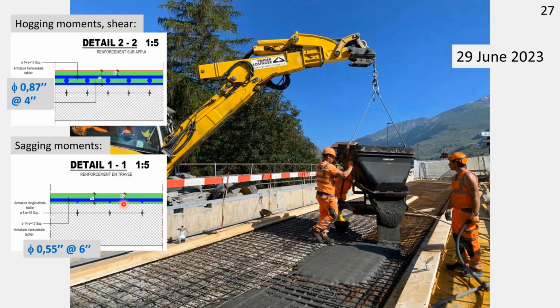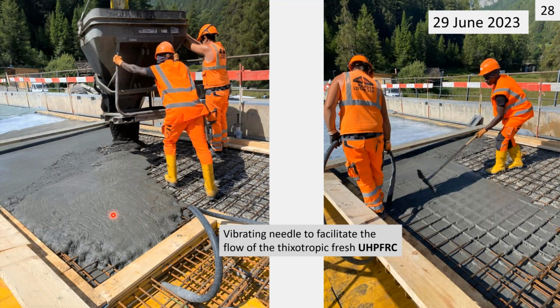Some other impressions, and you see here a vibrating needle. Of course, UHPFRC or UHPC is self-compacting material. It doesn't need to be vibrated. You should really not vibrate fresh UHPFRC. But here, the vibrating needle is just used in order to facilitate the flow, because we have a thixotropic mix, a thixotropic fresh material, because we have a significant slope of 5%. So we need a relatively stiff material that can hold this relatively high slope. And in order to be sure that at certain structural details, the material will for sure flow in all the little corners, we use a vibrating needle to facilitate the flow.